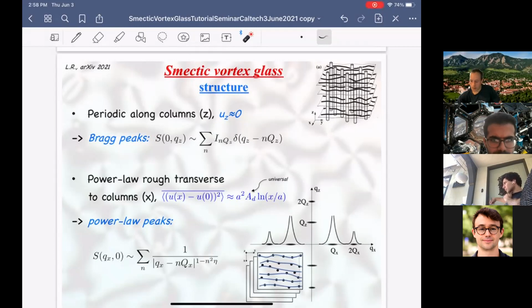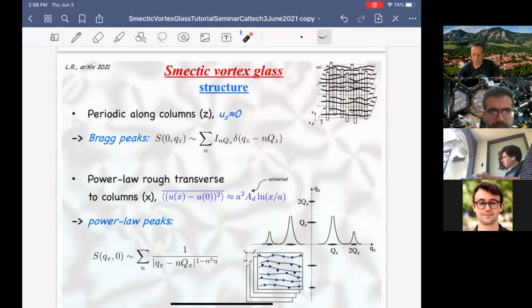So first observation is because the disorder is now independent of z, there's nothing that forbids, and in fact, at low temperatures, you will always have u_z, the distortions in the z direction, equal to 0. And that's because columns are independent, translation invariant in the z direction. So therefore, vortices will form periodic sheets in the xy, along the z direction. So there's actually a crystalline order in the z direction. That's why I call it a smectic.